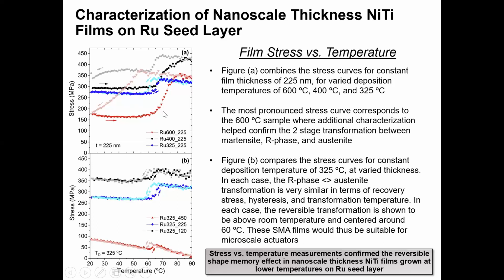So this one with the really big hysteresis, that wouldn't be too good to use for the... It really depends on what you're going for. Maybe some advantages of these narrow thermal hysteresis is you can get faster actuation. But like with anything, it's a trade-off. You're going to get faster actuation due to the narrow hysteresis, but you're compromising the recovery stress. And why that's significant is sometimes these larger recovery stresses are correlated to larger deflections. So there's a trade-off there, whether you're going for a fast actuation speed, like high frequency actuation, or if you want to really get large deflections.